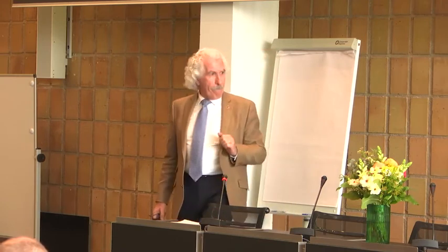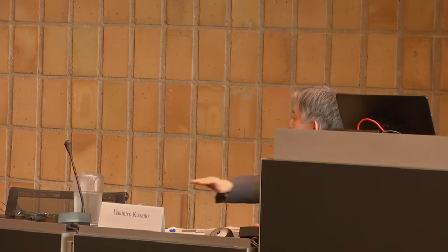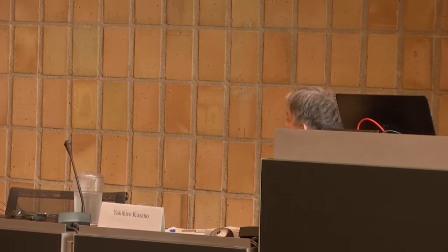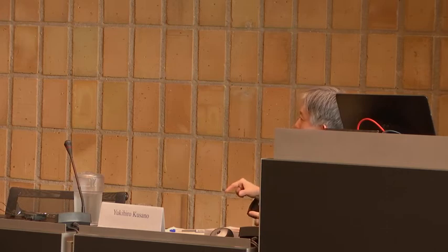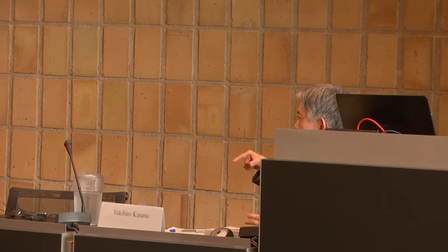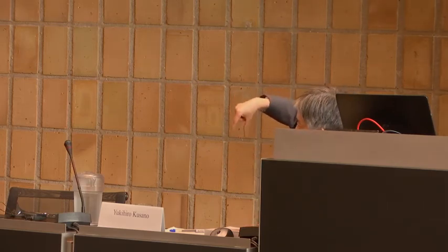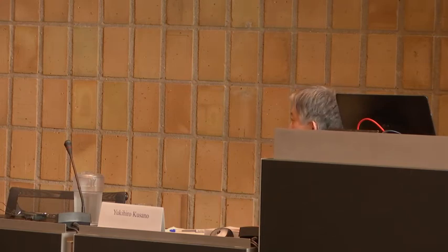Okay. Yeah, that's quite important. In my assessment, I always move the specimens and expose the surface a plurality of times, so that at least we can avoid somewhere which just accidentally wasn't exposed. But that was one thing. And the other thing is that, although I didn't do a lot yet, utilizing the opportunity for long extension, I also tilted the gliding arc so that the gas flow becomes much smoother than just approaching the surface vertically. But maybe it's not more for treatment effects. But yeah, basically.